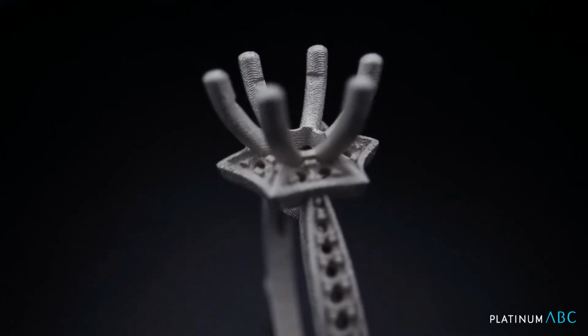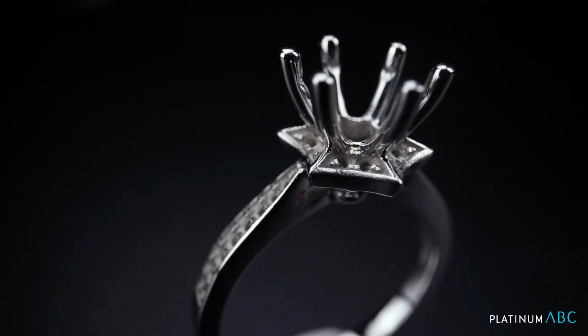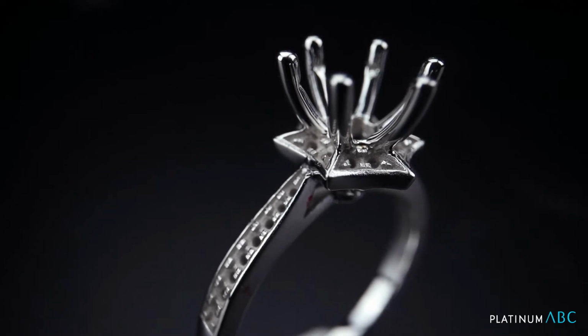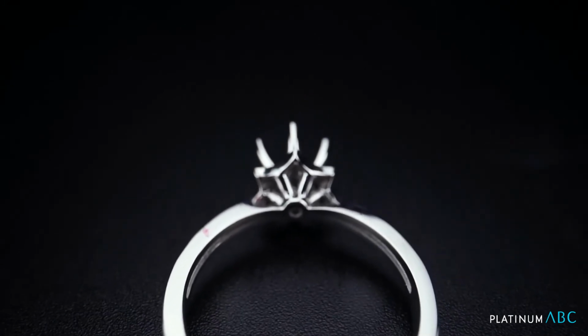Given the advantageous increase in hardness, being able to cast at 170 plus Vickers as cast, this platinum alloy is not harder to work with than any standard trade alloys out there, like platinum copper or platinum Ru. There's no indication that it has less fluidity, resulting in less fill, and there's definitely no evidence that adding the gallium would increase porosity. We're only adding about 3% to the overall mix. You're getting the benefit of a much higher hardness, plus the ability to control hardness through heat treatment during the production process.